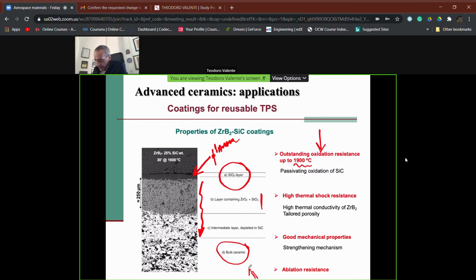That means the protection of what is beneath, up to about 2000 Celsius with a passive oxidation of silicon carbide, together with a very relevant thermal shock resistance due to the fact that zirconium diboride, which can be fabricated also by plasma spraying with a tailored porosity, has a very significant thermal conductivity for the ceramic class of materials, and this can reduce stresses which are related to thermal shock. Also assuring good mechanical properties due to the strengthening mechanism, which can be put in place by using a formulation which recalls the concept of ceramic matrix composites, and then also ablation, which is related with high temperature.